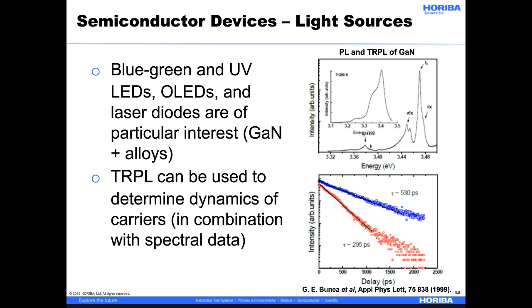Because the free exciton lifetime matches closely with theoretical calculations, and the fact that the data could be fit to a single exponential suggests that there's a very small number of defect levels in the sample, or that their relaxation time is very long.